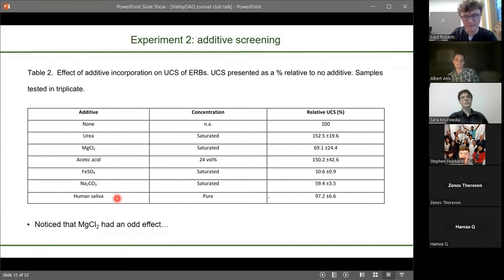And the reason for that is saliva was used with starch to make the glues I mentioned before to stick on arrowheads. So it has some effect on starch, chops it up, which can potentially make it gluer, stickier. And then we made these materials with these additives, and then just saw what the compressive strength was.